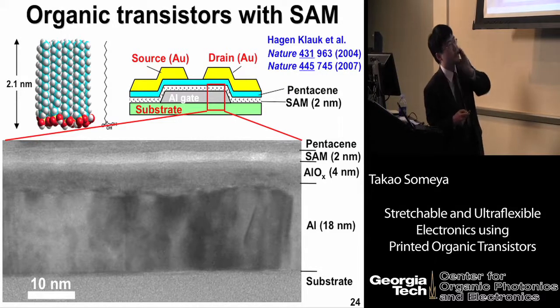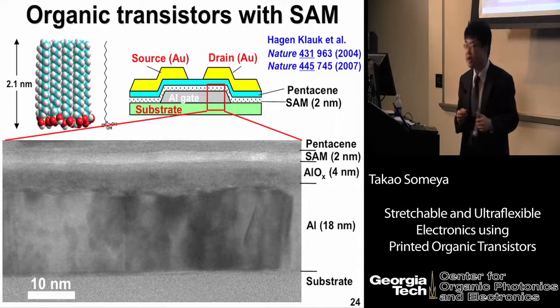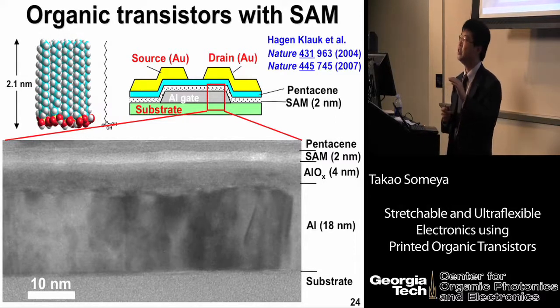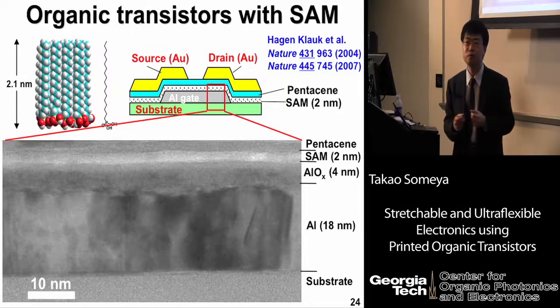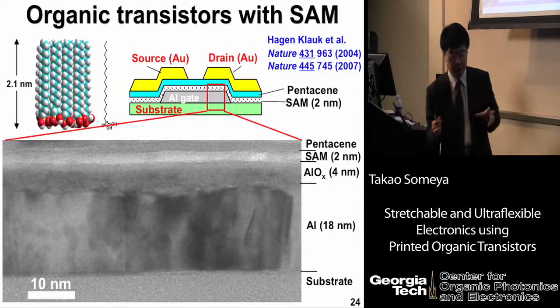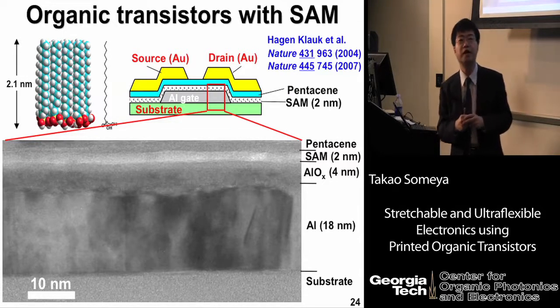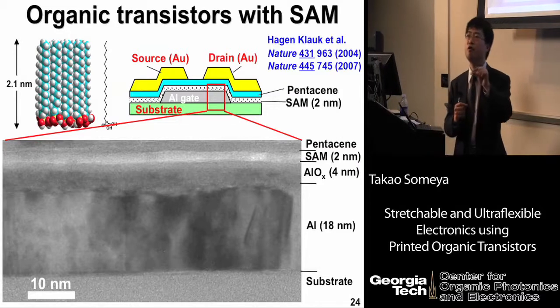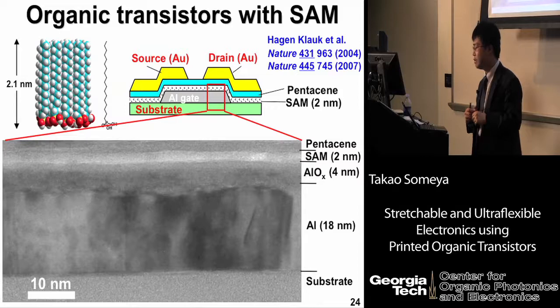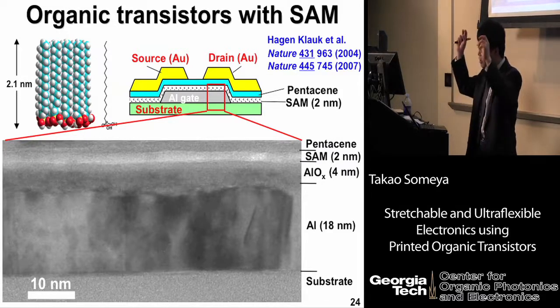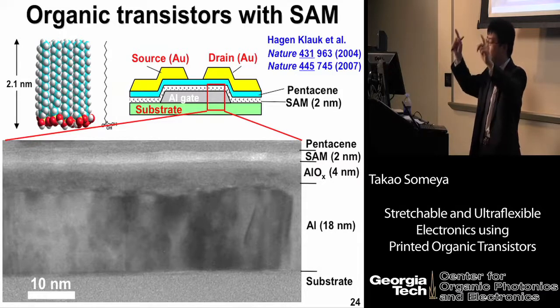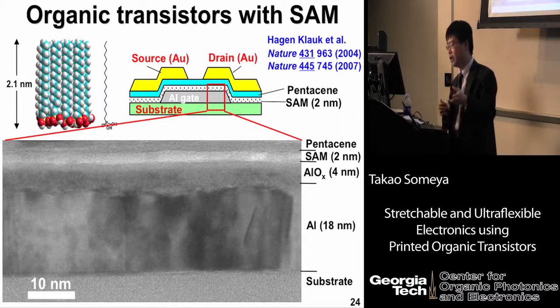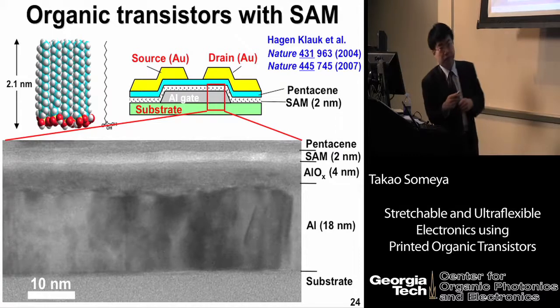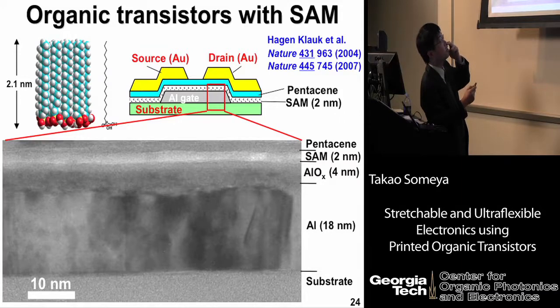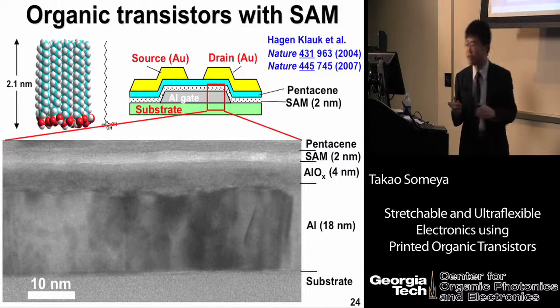Here is the substrate, and the aluminum gate is deposited by vacuum evaporation, and the surface of the aluminum layer is intentionally oxidized by plasma to form 4 nanometer thick aluminum oxide. Then this substrate is dipped into an organic solvent containing octadecyl phosphonic acid to form a 2 nanometer thick self-assembled monolayer. Then we deposit the pentacene or other semiconductor layer and print or deposit the gold as source drain electrode. So in this TEM cross-sectional view, you can clearly observe the abrupt interfaces can be nicely formed.